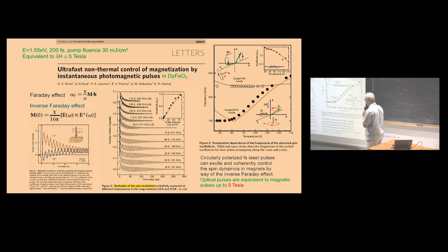And so it was, I think, the inverse Faraday effect was known for many years, but maybe forbidden. And in the last 20 years, again, it is used. In this case, the optical pulse is again in the visible range. And you can induce a magnetic field in pulses up to 5 Tesla. So it's quite a strong effect.